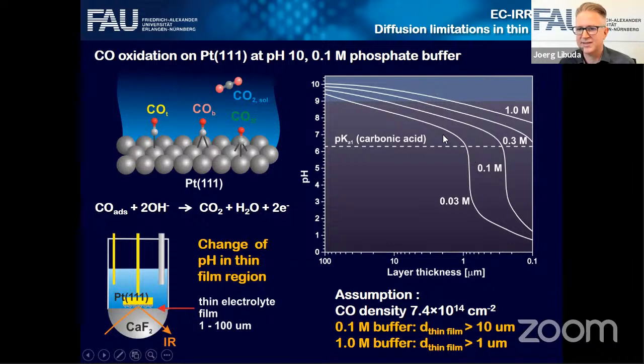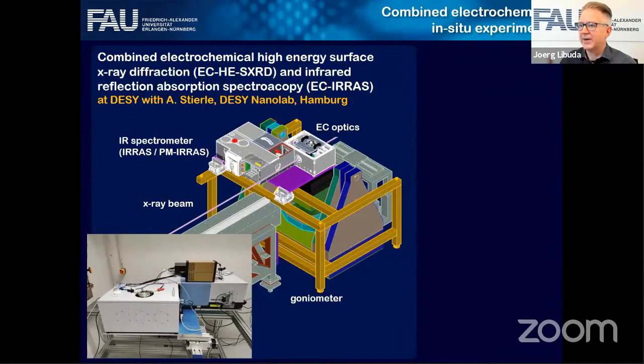Yeah, and you can see here if the layer thickness is thinner, let's say, than a micrometer or so, the pH changes can be dramatic. They can be dramatic when you run the reaction, and you have to keep that in mind. You have to make sure that the buffer is strong enough or the gap is large enough that you can really keep the electrochemical conditions. And I'll come back to that point. But let me just advertise one new experiment here. So I think this is a very powerful technique for surface chemistry.